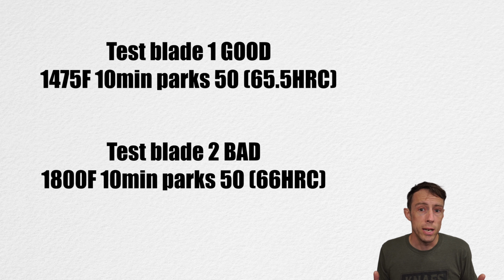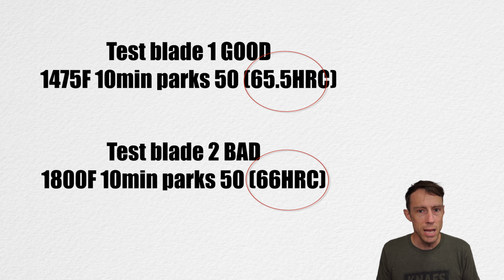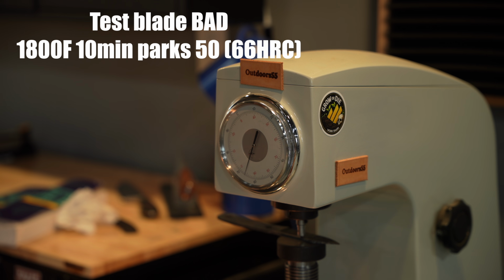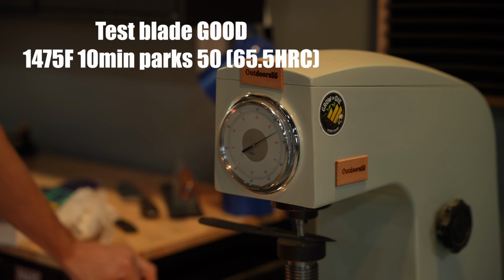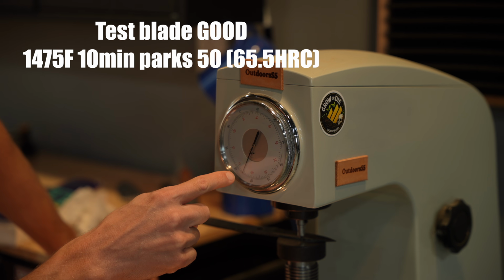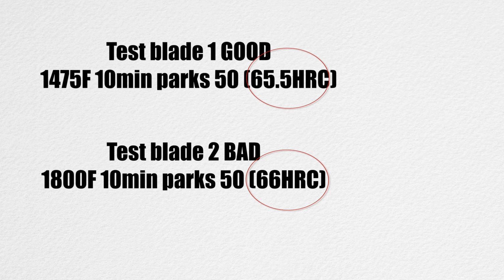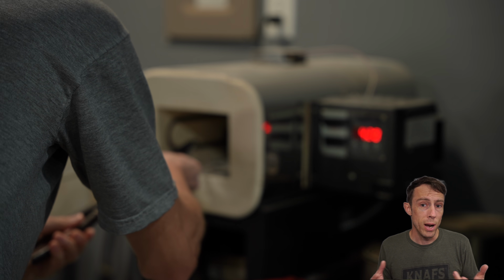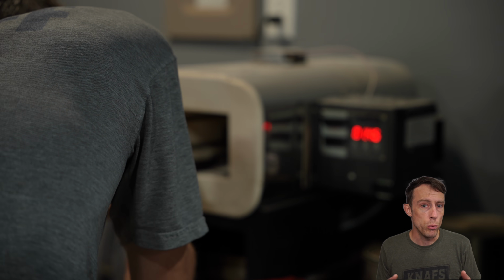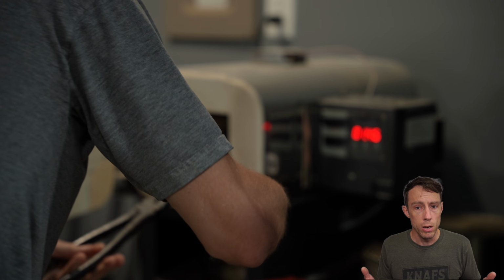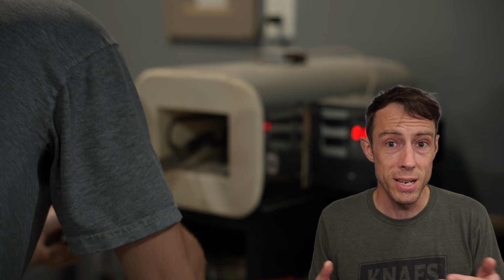Now the interesting thing here is that both blades' hardnesses tested almost exactly the same out of the quench. So this is the bad heat treated blade and it is 66 HRC. This is our good heat treated blade and we're at 65.5, so within a half a point of each other. And so I then tempered them exactly the same at 400 degrees and what do you know? The final hardness was exactly the same.